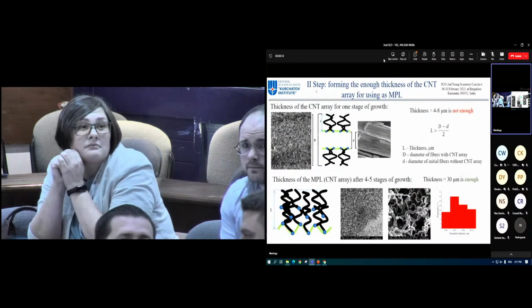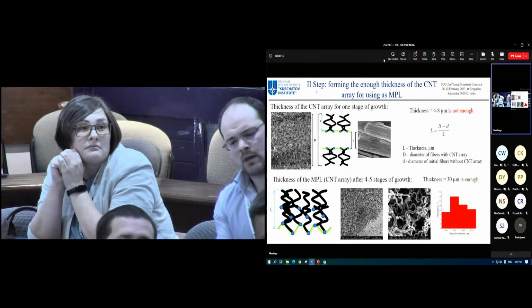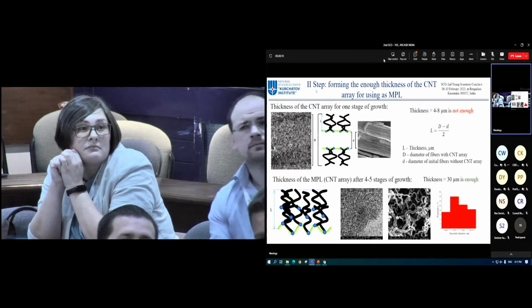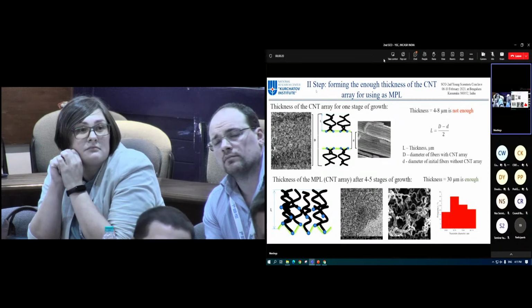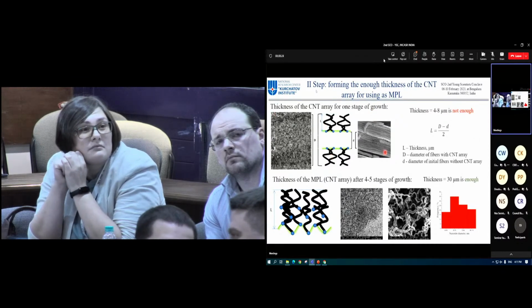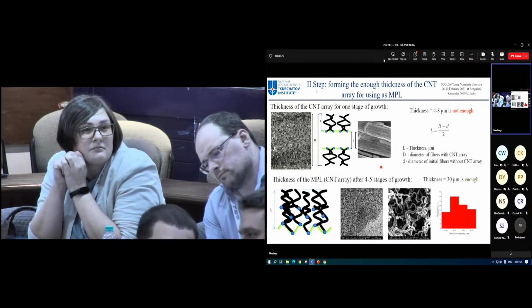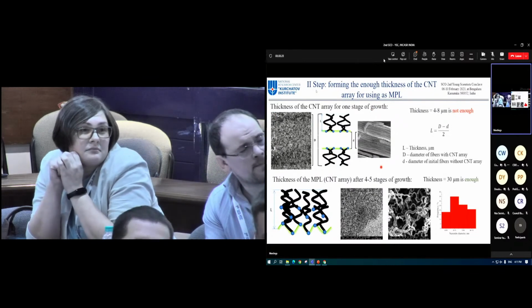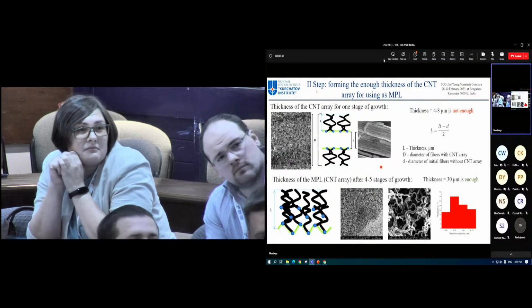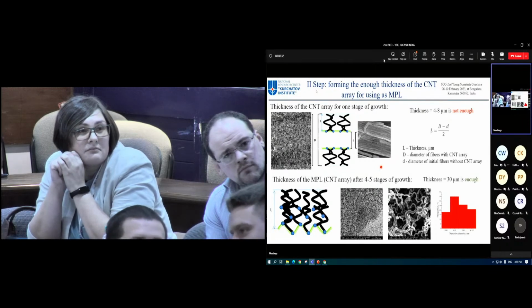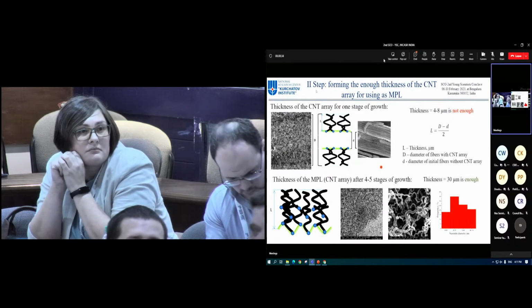The step is forming enough thickness of the CNT array for use as a microporous layer. As can be seen in the figure, the growth of the CNT array leads to an increase in the diameter of the carbon fibers of the initial gas diffusion layer, the change in which can be used to calculate this thickness.